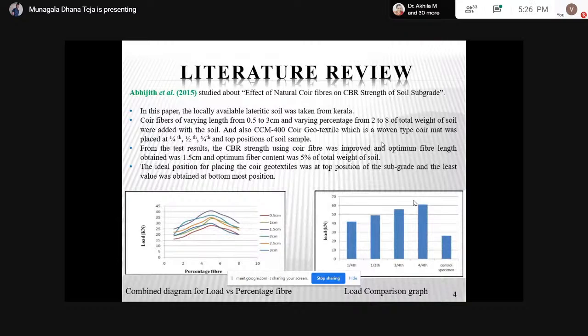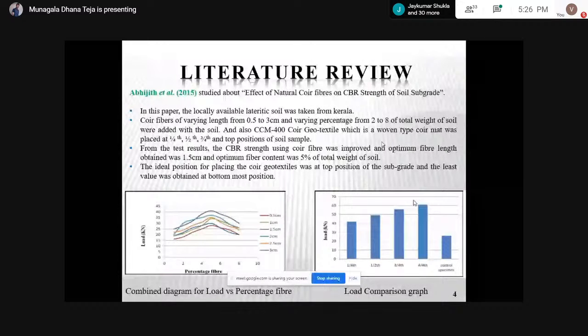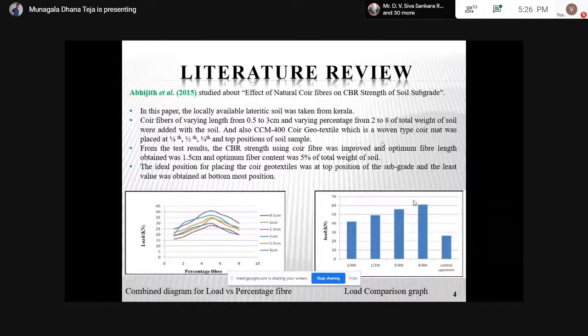The first is the effect of natural coir fibers on CBR strength of soil subgrade. In this literature, he used 0.5 to 3 centimeters of varying length and 2 to 8 percent of varying percentage of total weight of soil, and also used coir geotextile placed at different positions. He got better results at 5% and 1.5 centimeter coir fiber, and also at the top position of soil samples compared to other places.